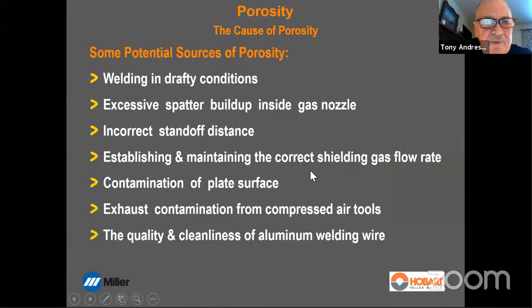But anyway, moving on. So potential sources: welding in drafty conditions, blowing away your shielding gas, is going to contaminate the weld. Excessive spatter buildup inside the nozzle, restricting gas flow. Incorrect standoff distance. All these are starving the weld from shielding, which contaminates from the atmosphere. Establishing and maintaining correct shielding gas flow rate.